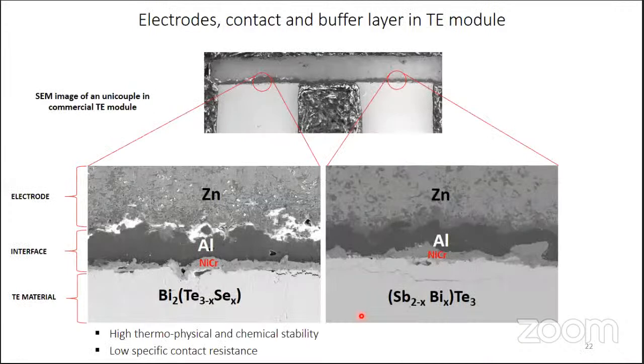And this microstructure I am showing here is just to explain how critical the hot side is. In one of the commercially available modules, which the supplier claims can be used up to 300 degrees Celsius, here, this is a hot side junction. Here you can see that. So this is a thermoelectric leg, P-type leg or N-type leg. Then it is connected with a metal, that is zinc. Zinc is used as an electrode.